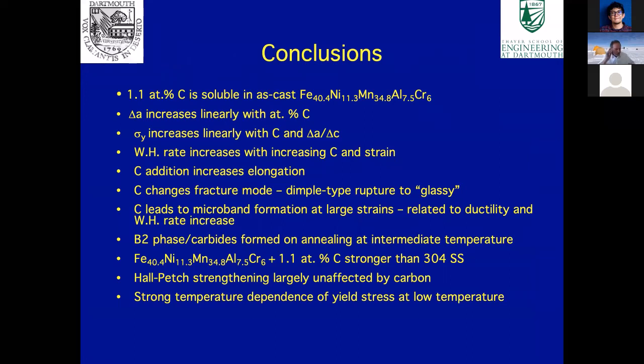So let me just summarize some of what I've told you there. What we found is that we can get up to 1.1 atomic percent carbon soluble in our as-cast high-entropy alloy. The change in lattice parameter increases linearly with carbon content, and the yield strength also increases linearly with carbon content and with the lattice strain as well. The work hardening rate increases with both the carbon content and strain, and the carbon increases the elongation of the alloy. It also changes the fracture mode from this dimple type rupture to a glassy fracture mode.